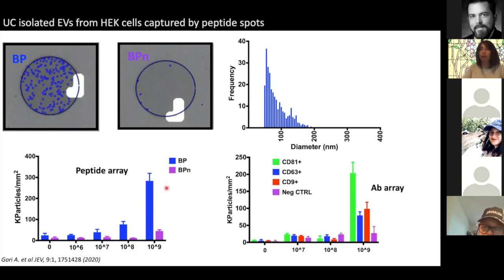Whereas the same samples incubated on an antibody array, a chip bearing antibodies anti-CD81, CD63, and CD9, allowed us to detect only the highest concentration, the 10 to the 9. So the comparison between these data suggests that the peptide array actually has a much higher capturing capacity compared to what is captured by the antibodies on this array. We speculate that this phenomenon is possibly due to a cooperative effect of multiple peptides acting simultaneously from the surface to capture and keep one of the vesicles on the surface of the chip. Whereas in the case of the antibody array, one antibody is able to find only its own marker.